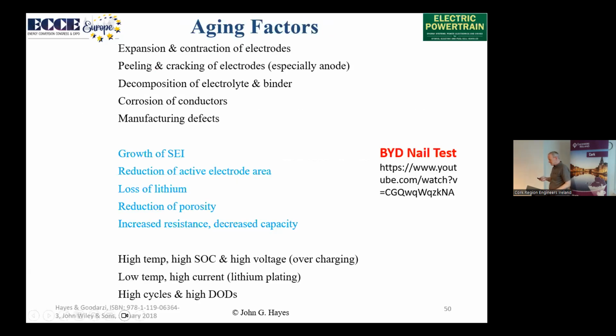Why does it age? It's going to age because the electrodes are going to expand and crack. We're moving a metal back and forth. It might only be moving 100 micrometers, but it's moving from cathode to anode, filling in and finding gaps, and it's going to cause some expansion and contraction every time it moves. We're going to get peeling and cracking of electrodes, especially the graphite on the electrode. It's just like the lead in a pencil. We're going to get a decomposition of the electrolyte and the binder that's holding it all together. These are all hydrocarbons. We're going to get corrosion of the conductors, and we're going to get manufacturing defects.